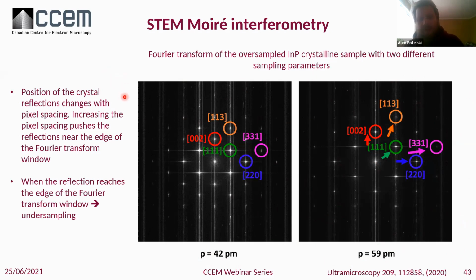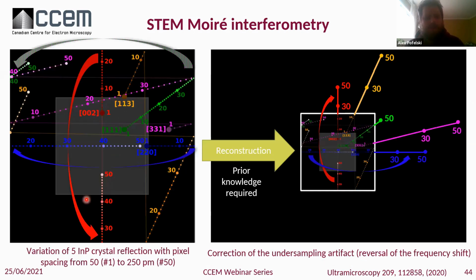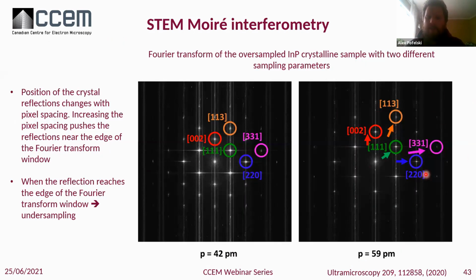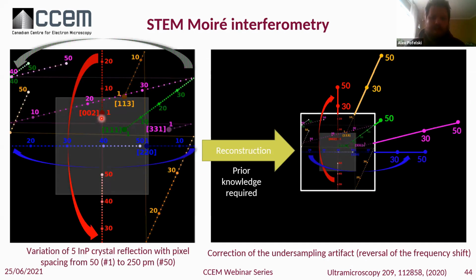So if we simulate that process for different pixel spacing, these are the same 5 reflections used for the indium phosphide crystal structures, simulated for a pixel spacing starting from 50 picometer to 250 picometer. So the number 1 is 50 picometer, and the number 50 is 250 picometer. So what is happening here? Let's take, for example, this 002 beam. The more you increase the pixel spacing, the more you get close to the edge.